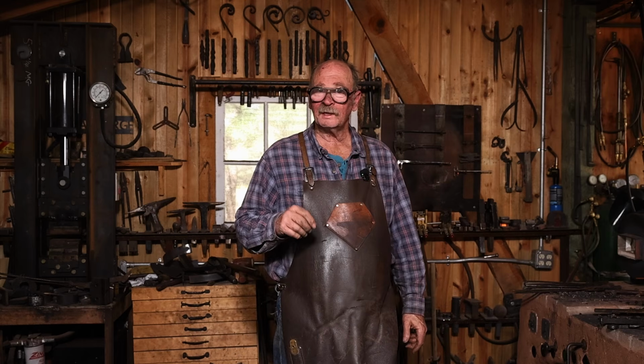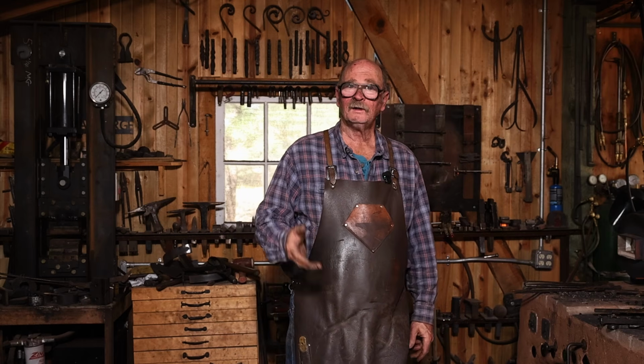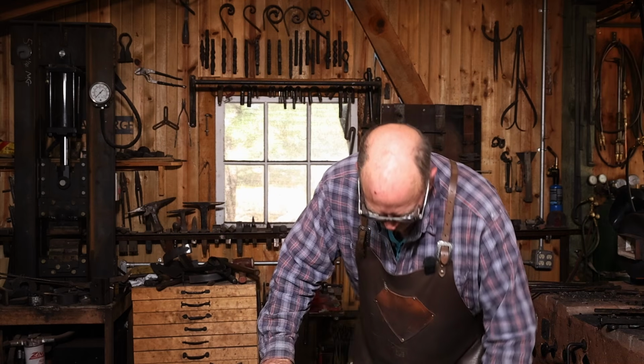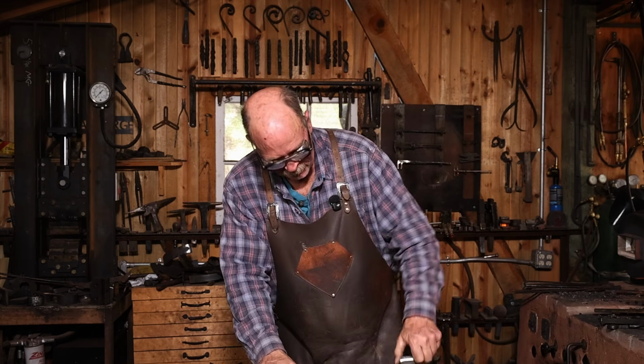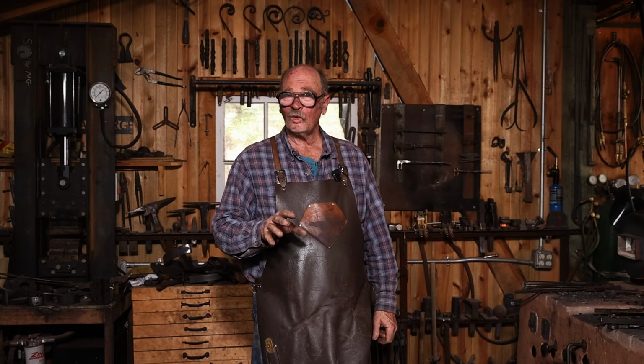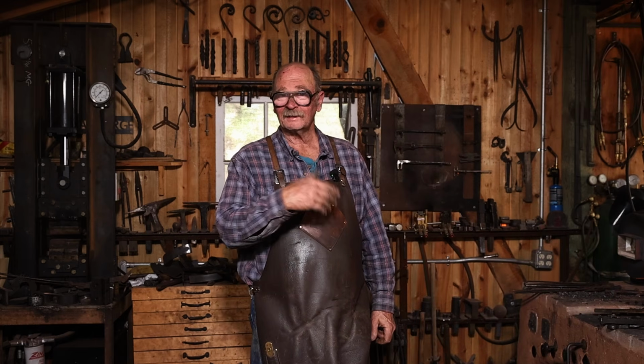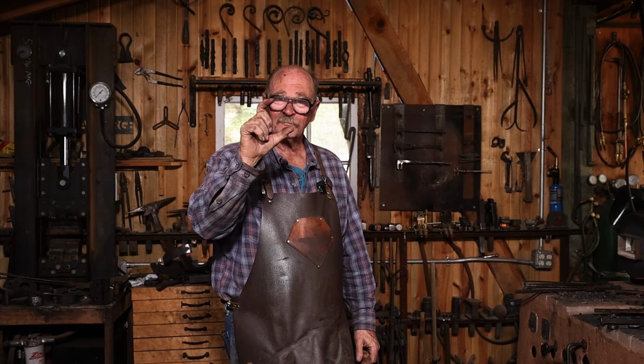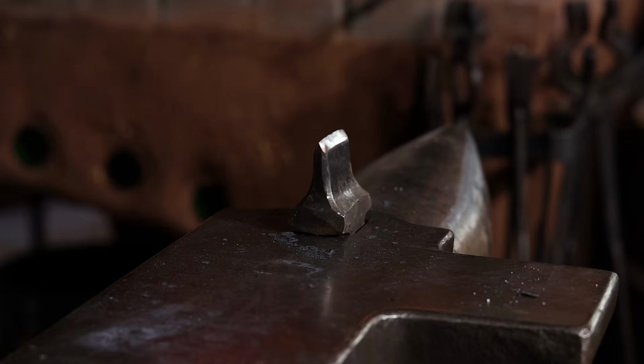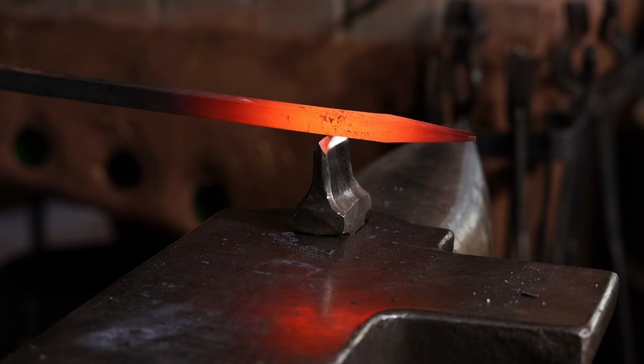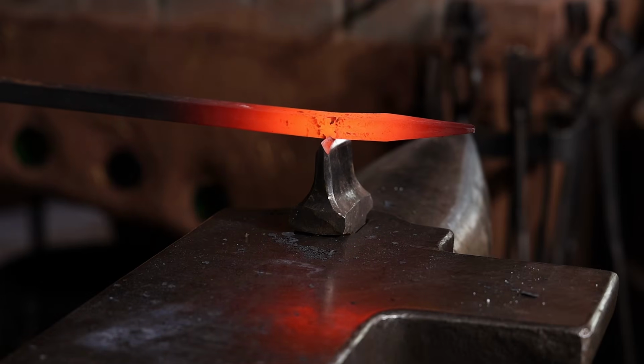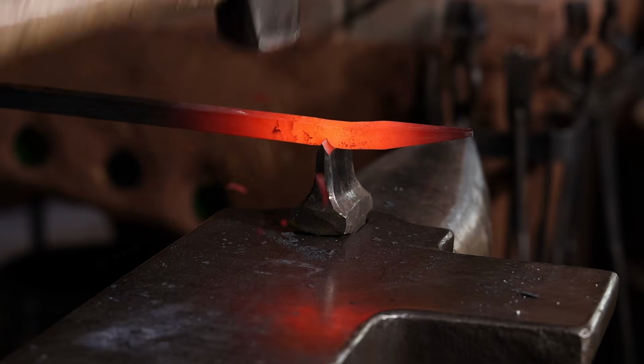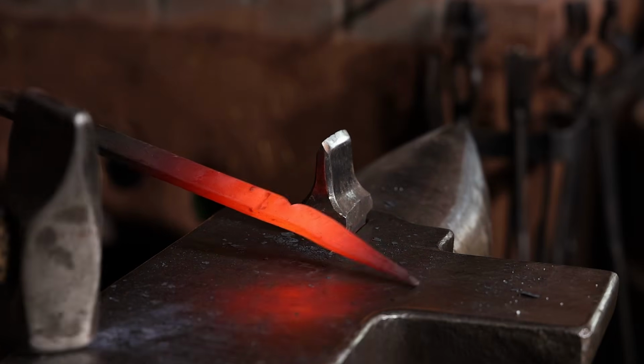Then we'll do the same nick halfway or so through the bar and fold it back on itself. For a poker, I don't want to leave as much material as I did for that first weld. I'm just going to fold about that much over. But you do want to make the weld in full thickness material because it draws out really fast at a welding heat.